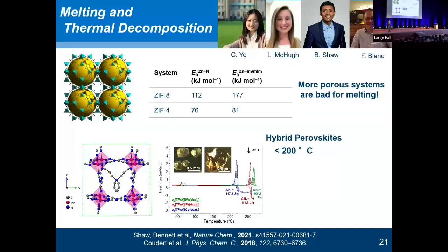We can say, okay, porous systems don't melt. Dense systems, like these hybrid perovskites, still a MOF-type of system, with manganese octahedra, dicyanamide ligands and an ammonium cation, actually melt at around 200 degrees, so even lower. Hybrid perovskites are kind of another hot material, rivaling MOFs for this everybody-loves-them status. But we can show that these melt.